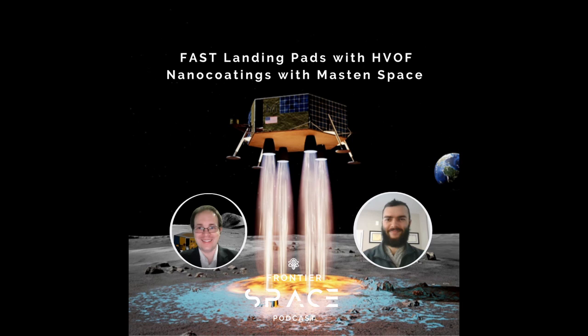Another series of tests we did focused on how this material actually performs when you hit it with a rocket engine under landing conditions. So we took one of our engines, 100-pound thrust, which equates to a fairly decent sized lunar engine. When you do a conversion to heat flux in a lunar environment, you get very different performance when you're in a vacuum. So it's a much harsher test environment here on Earth. And we have a very, very cool test stand that actually lowers while the engine is firing. So you can directly simulate the trajectory of a spacecraft landing on the lunar surface. We've been using that for some testing with NASA, and it's just brilliantly cool.